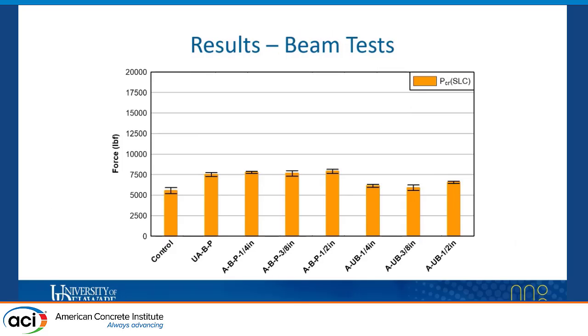Okay, so the orange beams demonstrated here are the load at which concrete cracking initiates for the SLC group. You can see that the anchored bonded beams demonstrate cracking load consistent with the unanchored strengthened beams, whereas the unbonded anchored beams demonstrate a load of concrete cracking consistent with the unstrengthened beam. The reason for this being that the applied flexural strip for the unbonded beam doesn't engage until the anchors do, which is after the fact that concrete has already cracked.